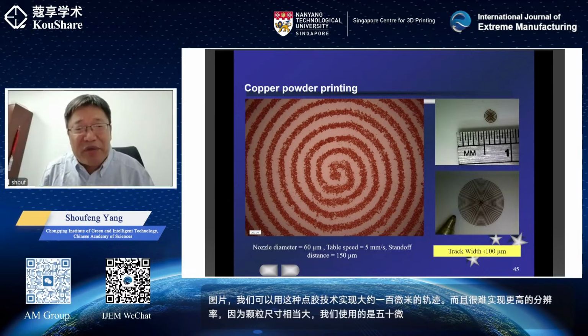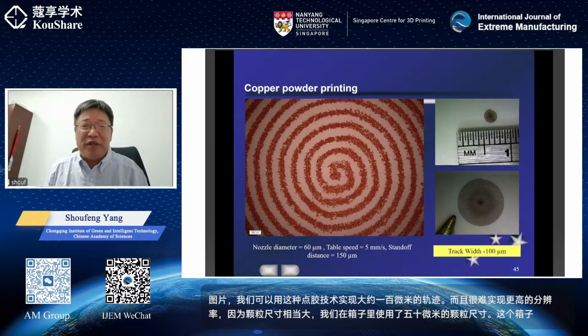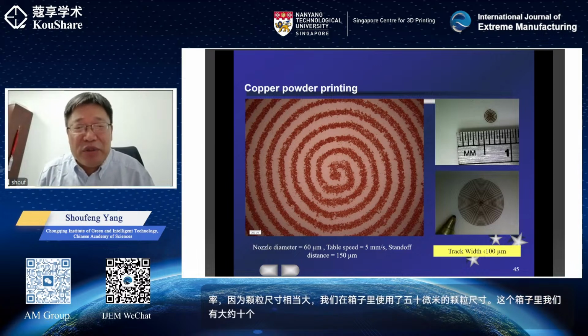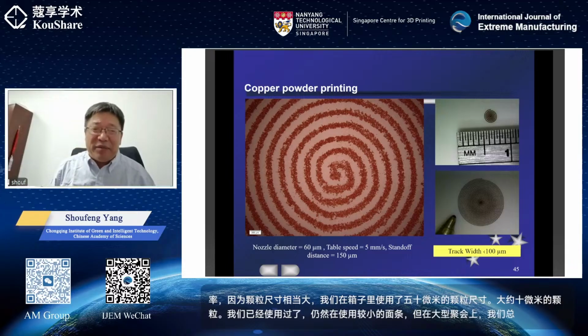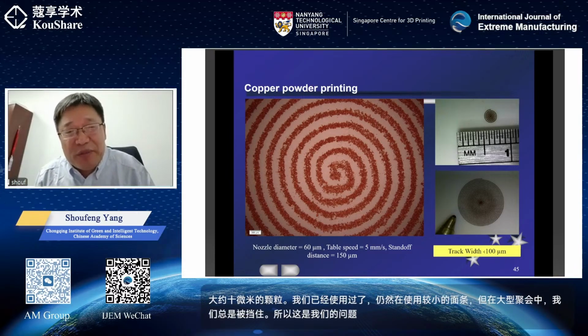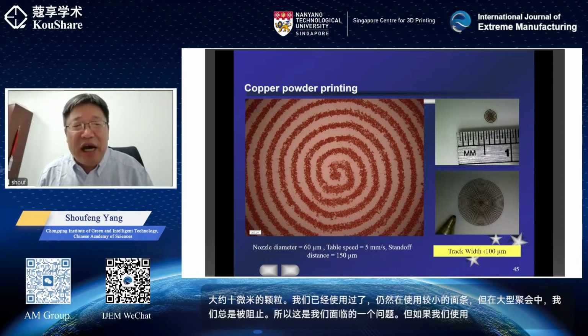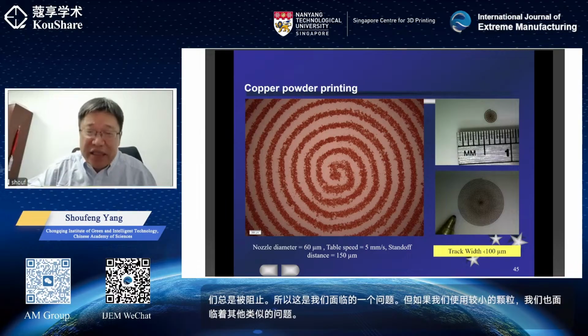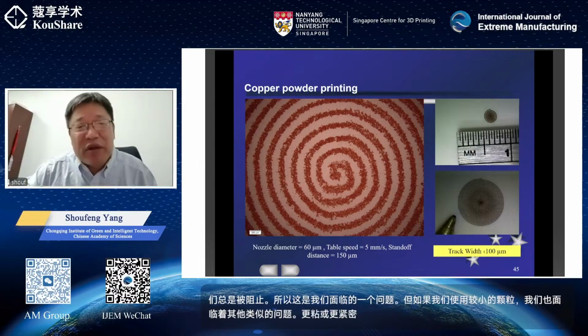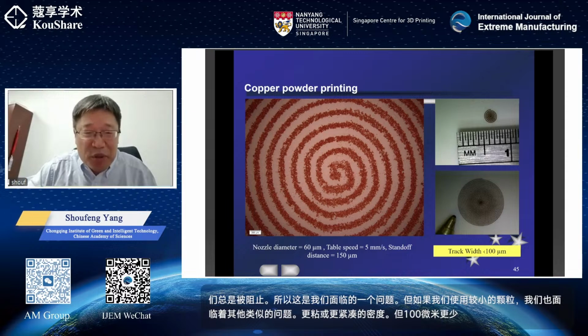In this case, we have to use about 10 micrometer particles. If we still use smaller nozzles but with big particles, we always get blocked. So that is a problem we are facing. But if we use smaller particles, we also face other problems, like it's more sticky or has more compact density. But 100 micrometer is more or less enough for powder bed-based additive manufacturing, because we know the spot size of the laser is about 100 micrometer.